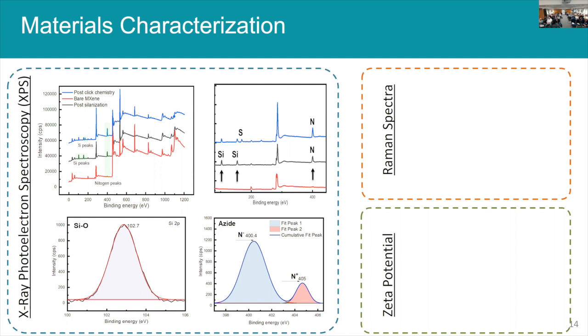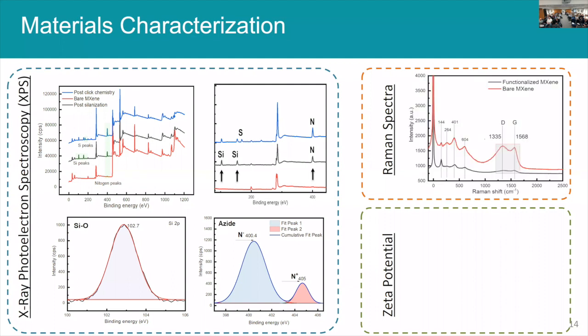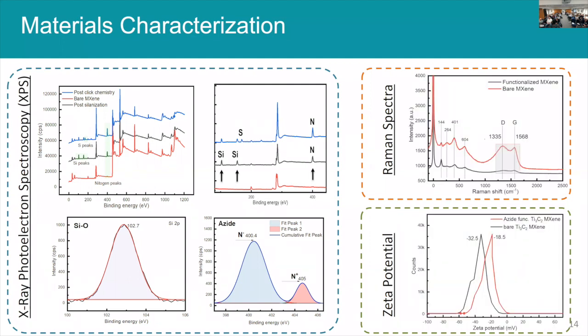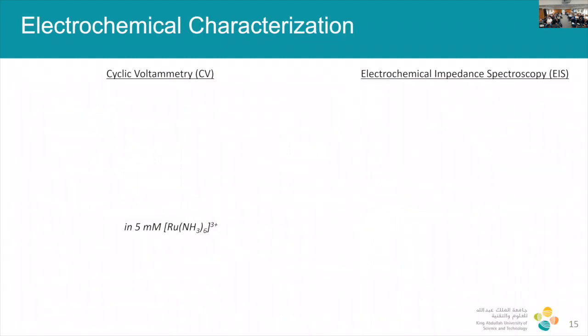XPS can also be used for semi-quantitative analysis, so we should be able to work out the exact mole percentage of this PNA on the surface. Our preliminary results are telling us it's like 5 mole percent, but we're going to confirm that later on. We did Raman spectroscopy and also zeta potential comparing the bare and functionalized. We see great, significant differences as we expect. So I'm going to skip this and get to some of the electrochemical characterizations.